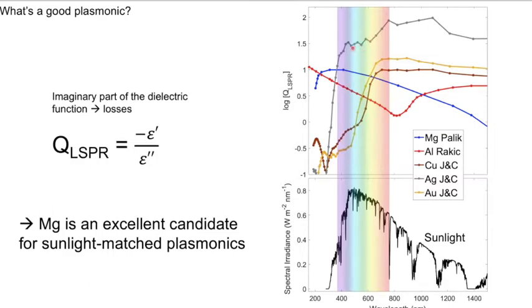Okay, the problem with silver, again, it is quite rare. And it oxidizes very readily, and it oxidizes without forming a protective oxide. Magnesium is essentially next in line, right? Very good performance in the blue and the purple and the green. And you can see that magnesium basically beats the other abundant element across the entire visible range. So that's why we really started to look at magnesium, because it's an excellent candidate for sunlight matched plasmonics.